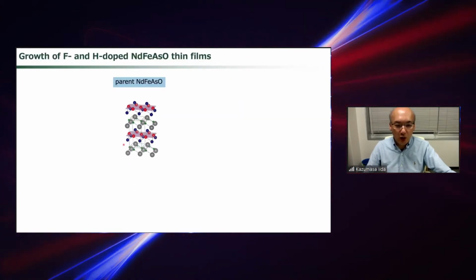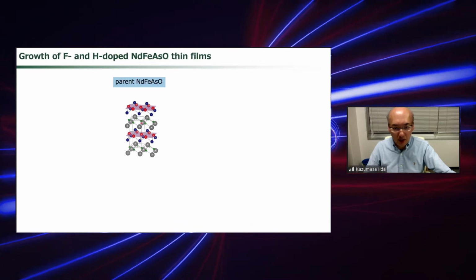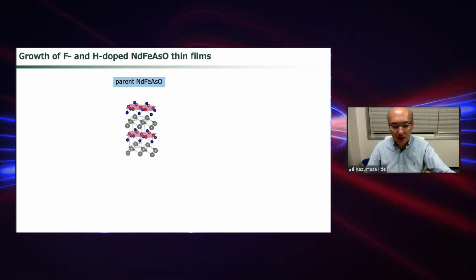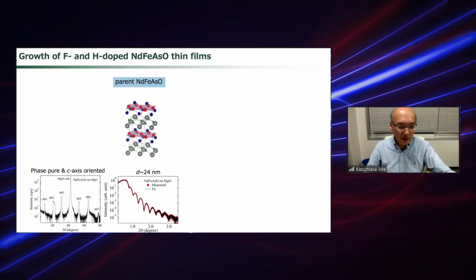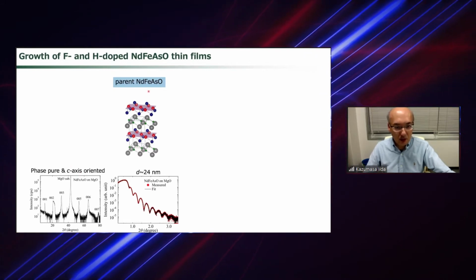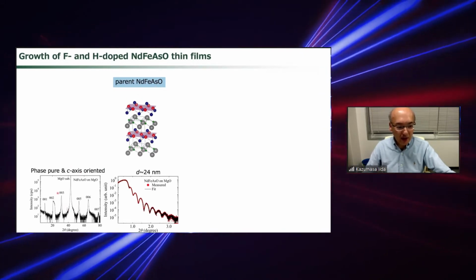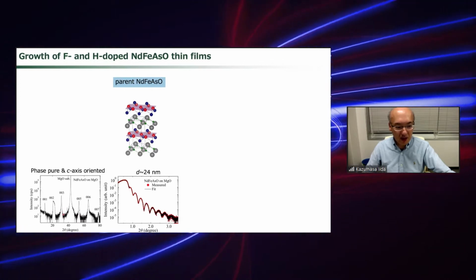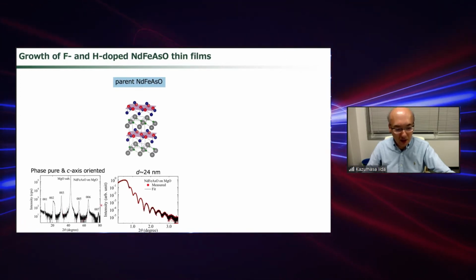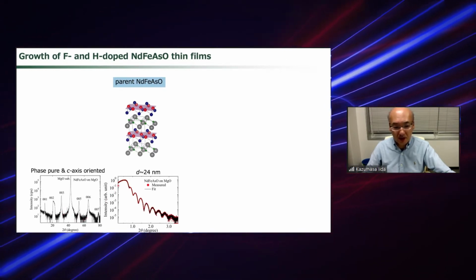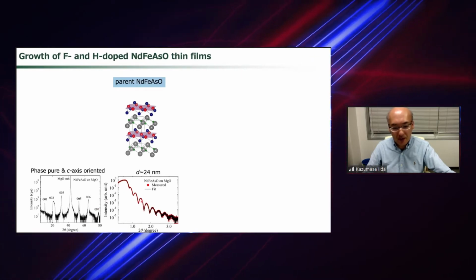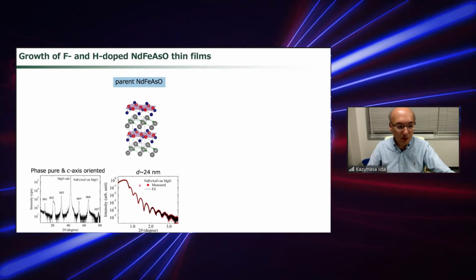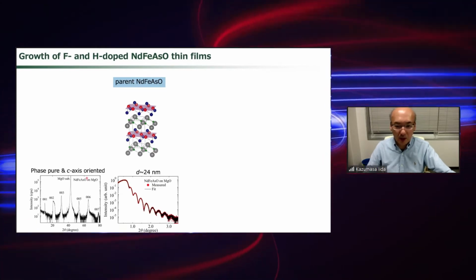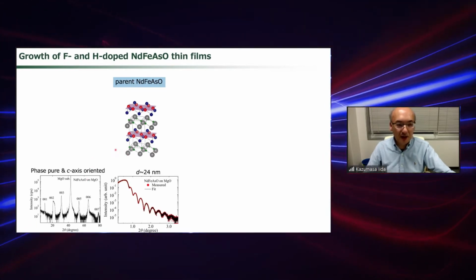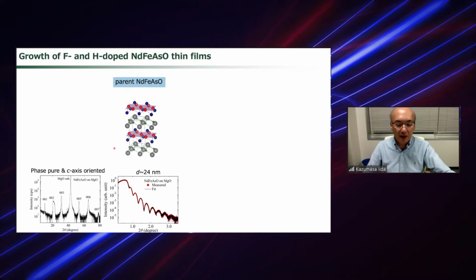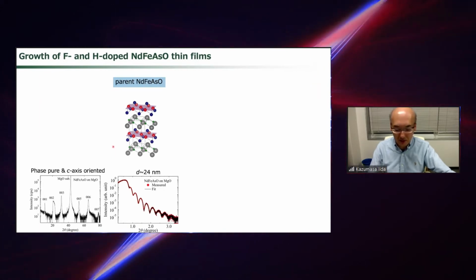And we employ this method to incorporate hydrogen into the films. First, we prepare the parent compound of the neodymium iron arsenic oxide. And here are very nice C-axis textures of the films obtained. The film thickness was evaluated by X-ray reflectivity, which shows around 24 nanometers. For comparative studies, we also prepare the fluorine-doped 1111 thin films.